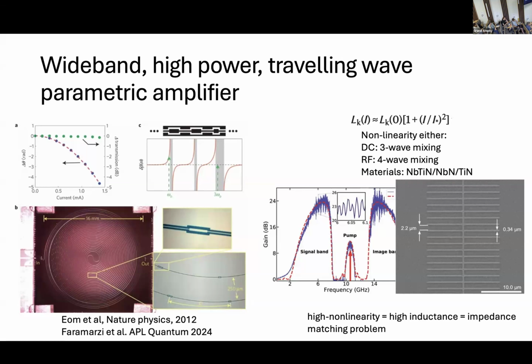One of the funny things is that if you want to get to higher nonlinearity, which they tried to do recently, you want to make this wire narrower and narrower. Obviously you then get a larger impedance, which is what you want, but it's also annoying because at the end of the day you want to amplify a signal that comes from a 50 ohm line. That's why these days the devices typically look like this. You can do it in various ways, but this is the line on which you send the current and get amplification, and there is this whole structure to create enough capacitance to balance this out and still have a 50 ohm line. There are all kinds of variations where people put resonators next to it, or IDC type capacitors, to balance out the impedance mismatch in essence.